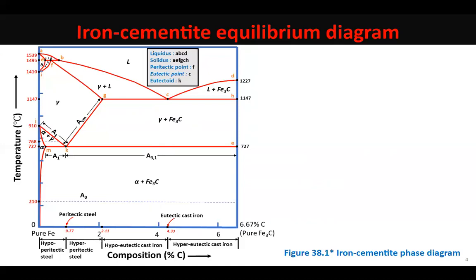Now students, the second question: which of the iron carbon alloys undergoes this reaction completely? That iron carbon alloy is said to show this reaction completely which, just above 727 degrees centigrade, contains 100% austenite, so that after the eutectoid reaction, below 727, it contains 100% pearlitic structure. That condition is met by the 0.77 percent carbon steel. Just above 727, it has 100% austenite in it, single phase austenite.